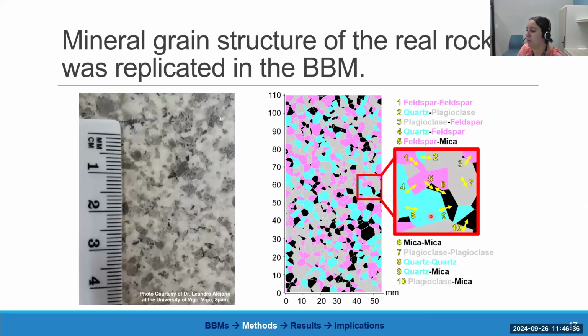Yep. So we have 10 different contact types here. They're the ones listed here on the right and labeled in this inset. So each pairing of blocks has a corresponding contact, and their contact properties can be different. So they have stiffness values, and that includes joint normal and joint shear stiffness. And then they also have strength values. So we specifically use the Mohr-Coulomb failure criterion. So they've got cohesion and friction angle, and we did strain softening too. So peak and residual cohesion and friction angle values.